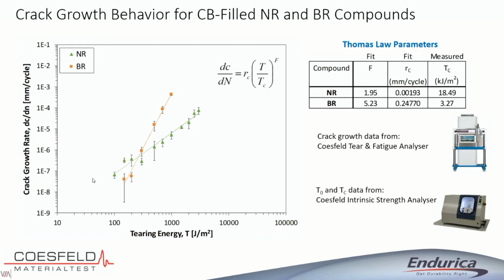Now let's apply the method to two materials that we know a lot about. So natural rubber and butadiene. What you're looking at here are fatigue crack growth rate curves for these two materials. What's interesting to compare is they have a different power law slope F, right? I've characterized that here. I've got a table that shows the tear strength values TC. Natural rubber is much stronger than butadiene by about a factor of 6.